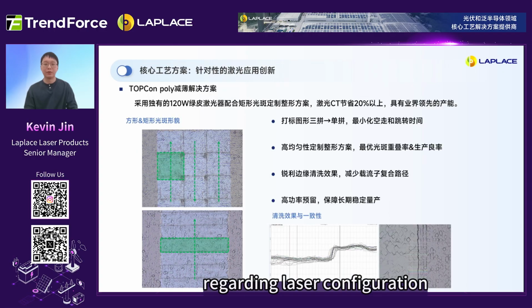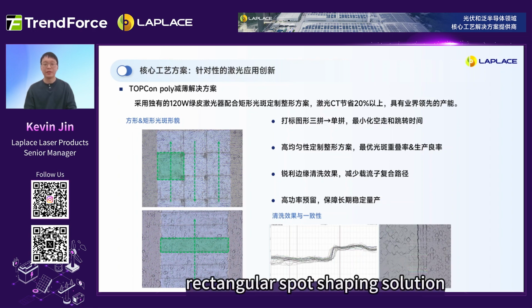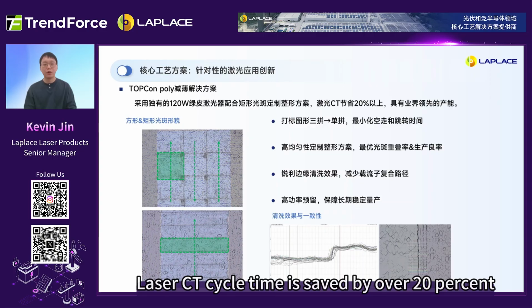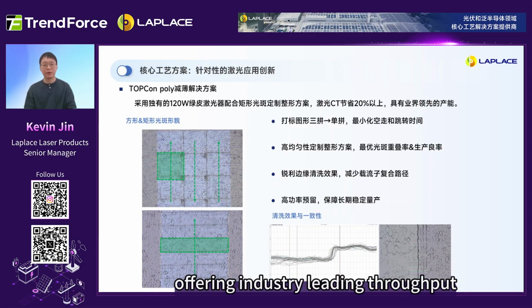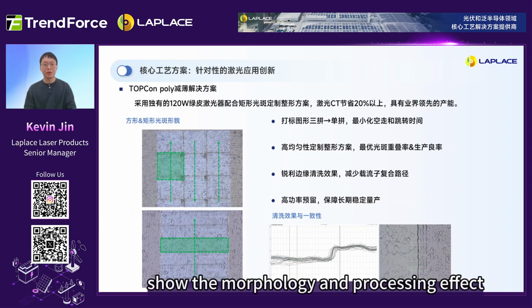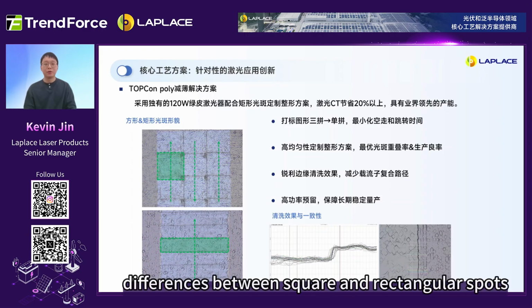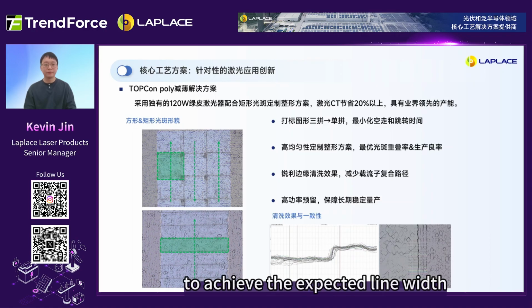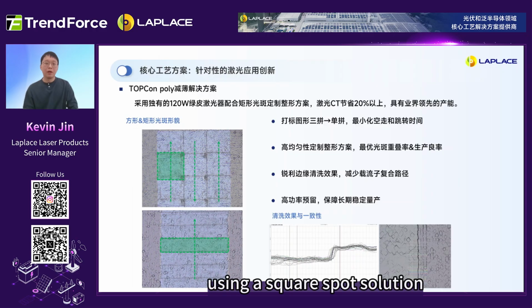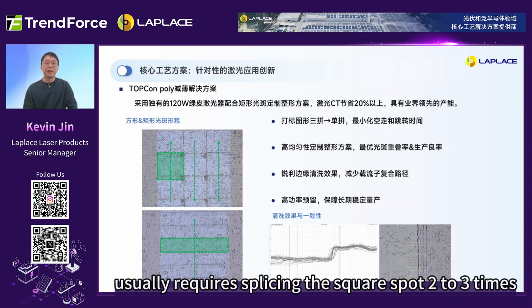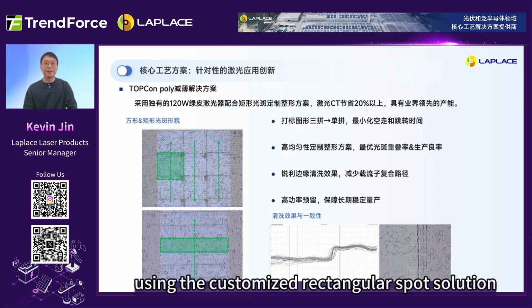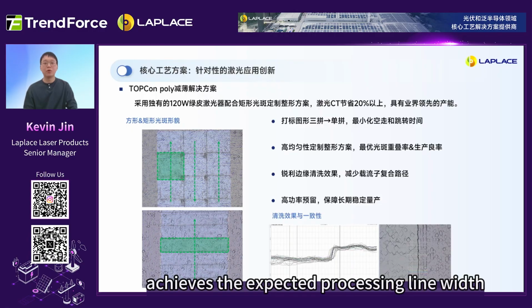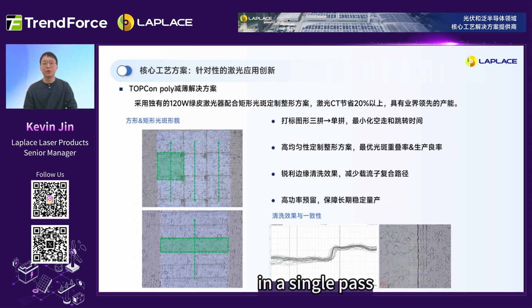Regarding laser configuration, Laplace uses a unique 120W green picosecond laser combined with a customized rectangular spot shaping solution. Laser CT cycle time is saved by over 20%, offering industry-leading throughput. The two images on the left show the morphology and processing effect differences between square and rectangular spots. In our polythinning application, to achieve the expected line width, using a square spot solution usually requires splicing the square spot 2 to 3 times. Using the customized rectangular spot solution achieves the expected processing line width in a single pass.